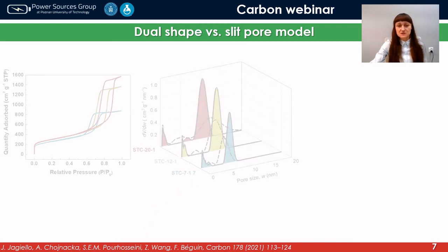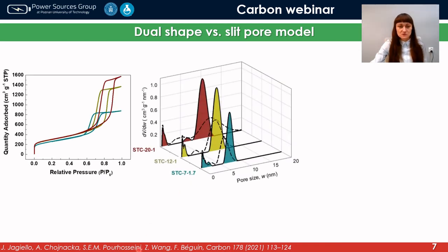To compare the dual shape model with the slit pore model, we applied the dual shape model to the samples which I showed you at the beginning. So the samples in which we used the silica diameter of 7, 12, and 20 in the precursor mixture. And here we can see the pore size distribution results calculated from the slit pore model. This is the result represented by the dashed black line, and the results obtained from the dual shape model are represented by the solid black line.